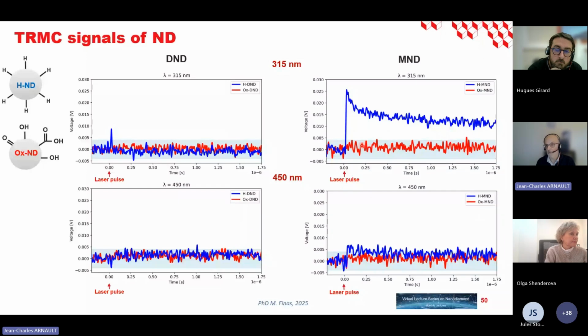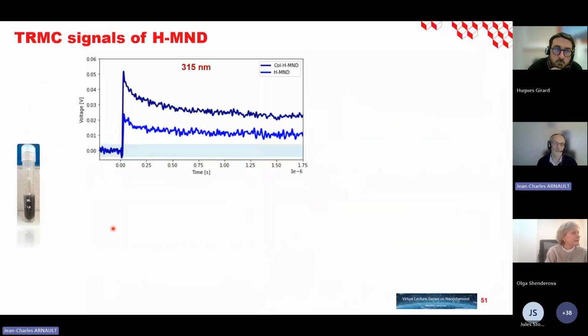Nevertheless, when we look in the visible range, the signal is very close to the detection limit, as you see here. So this is what we got for the four kinds of particles. But there is an additional result. I said that all the previous measurements were done on the powder just after treatment.